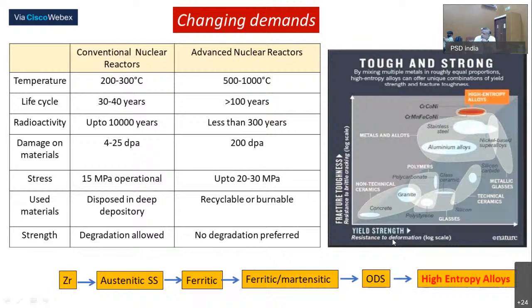Why are these high entropy alloys very important? You can see in the graph which I am showing over here that if you draw a graph between yield strength and fracture toughness, the high entropy alloys sit right on the top. They have adequate yield strength and very high fracture toughness, and that is why these alloys are one of the best proposed alloys for future reactors.